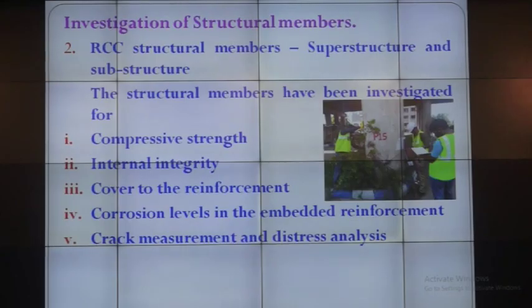Then the structural members, superstructure and substructure, are investigated. What parameters have they been investigated for? What we have done is compressive strength. We have determined the compressive strength by removing cores from the superstructure. Internal integrity is the same. Ultrasonic pulse velocities have been tested at regular intervals. And cover to the reinforcement. Yesterday I told you it is a profometer. We kept the profometer and took the cover, because that plays an important role in the durability of the structure. So the cover to the reinforcement has been taken.